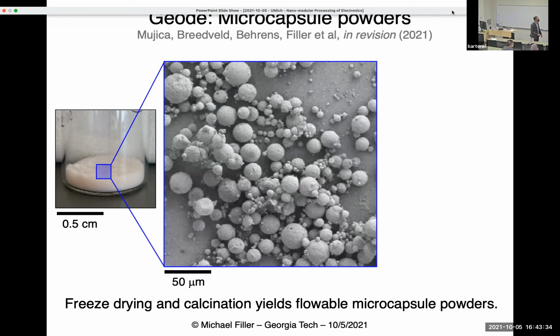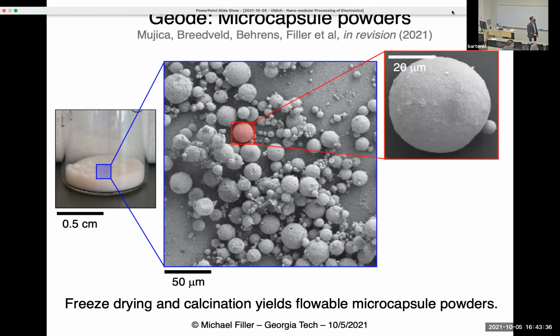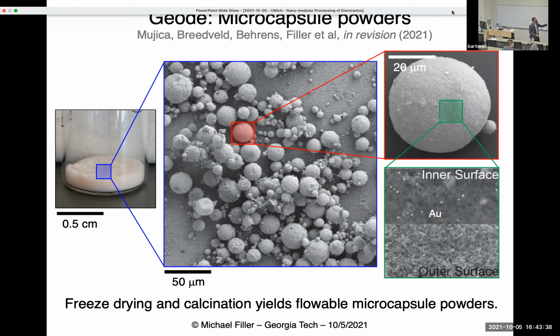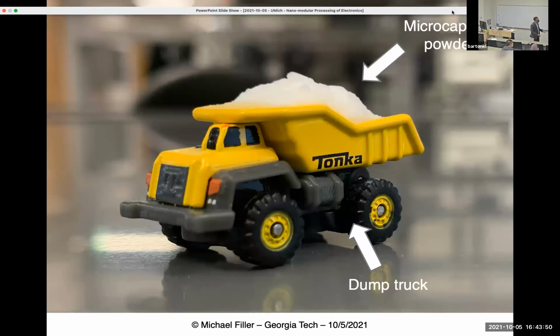In the SEM, these are what those capsules look like. And you can break them open and look at the interior surface, and you can see the metal seed particles. And the exterior surface has very few of the metal seed particles. They're largely on the inside. And so we filled a dump truck with these. That is a very small dump truck, but we have still filled a dump truck.